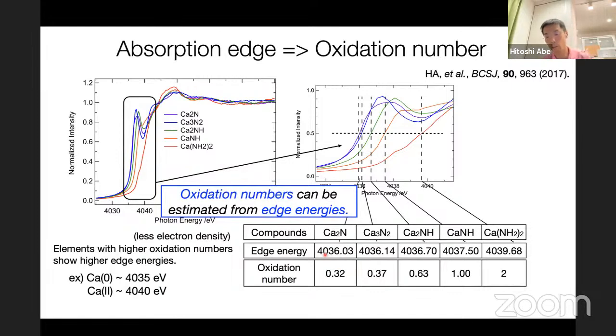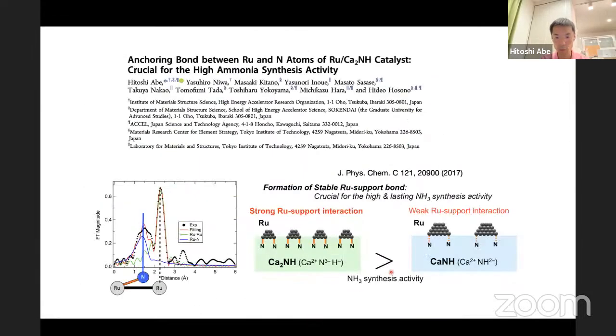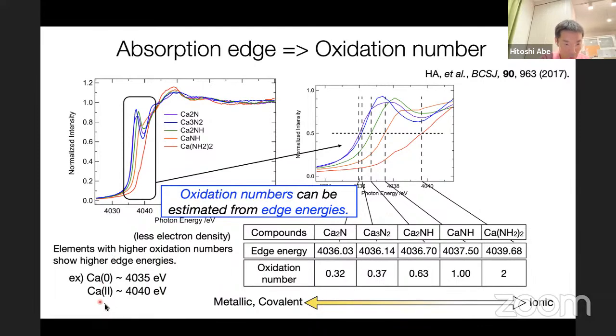I won't go into details of how to analyze these edge energies, but we obtain the oxidation numbers by analyzing these edge energies, considering that calcium NH2 has a 2+ state. So you see here, for example, the calcium in Ca2N has the actual oxidation number of 0.32. Okay. So an oxidation number close to 0 means metallic or covalent, and an oxidation number nearly 2 means an ionic state. So we can analyze the real oxidation numbers by analyzing absorption edge energies.